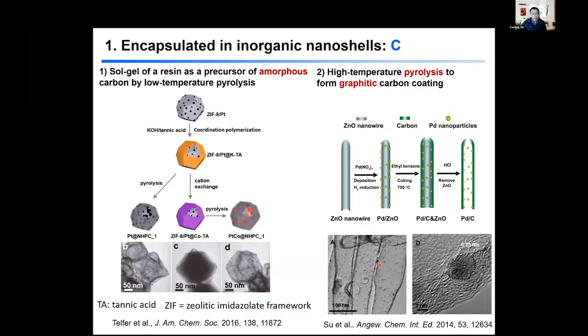Okay, and the last example of inorganic nanoshell is carbon, and the way to produce carbon coating is also typically through a conversion reaction. For example, we coat the particles with coordination polymer, in this case potassium tannic acid, and the original particle was ZIF, basically MOF particle, decorated with platinum nanoparticle. So we basically wrap them and then pyrolyze the system, and then the polymer is combusted. ZIF actually is also combusted, and we produce platinum particles inside a capsule of carbon.